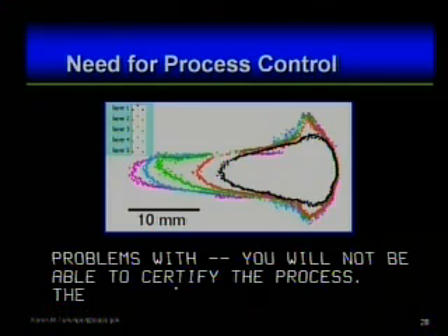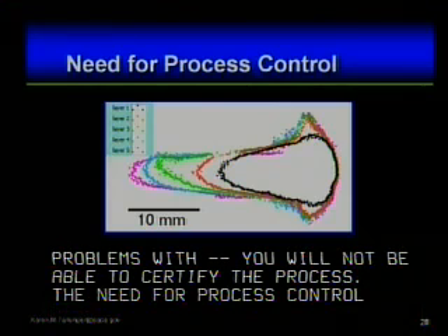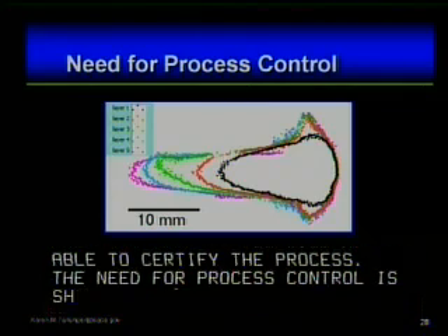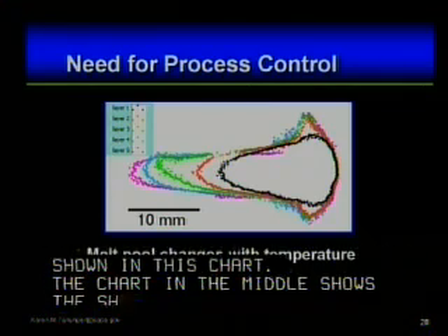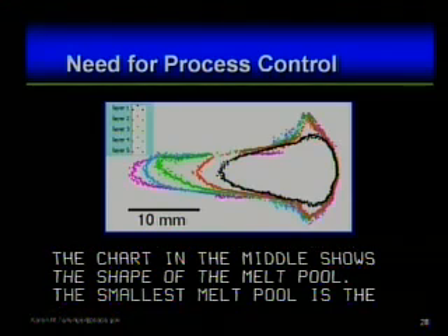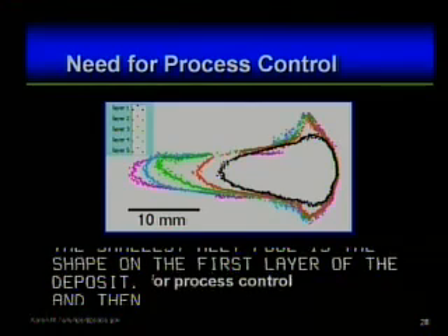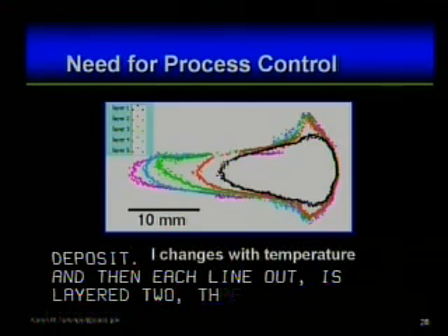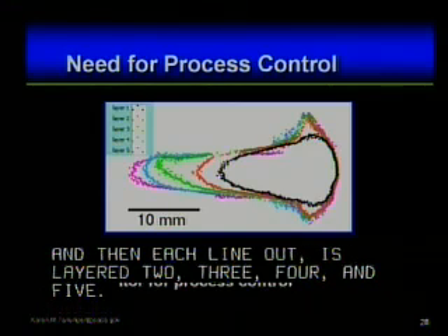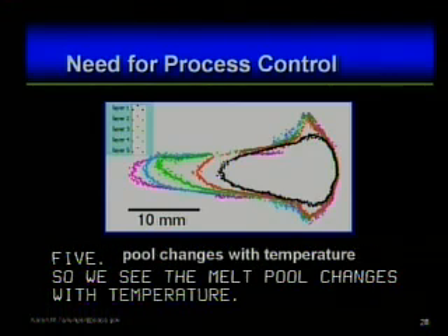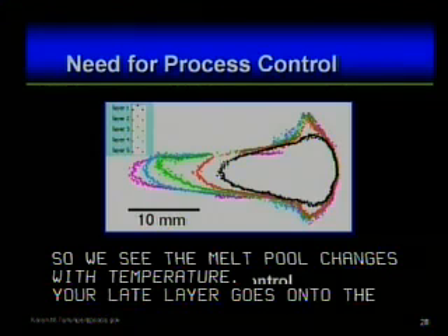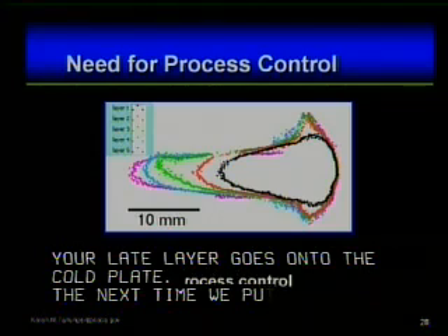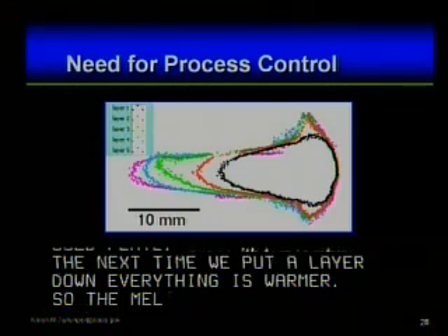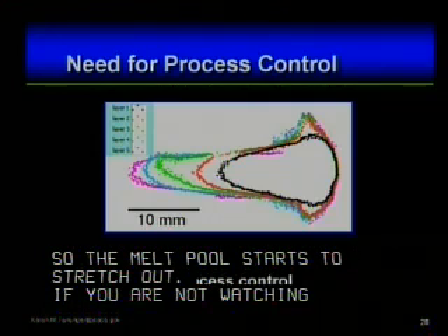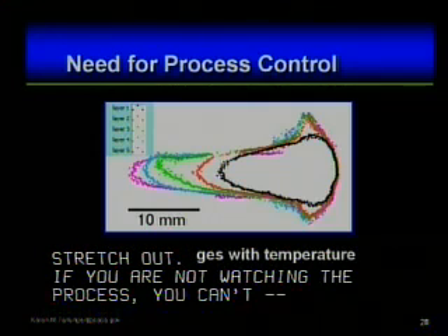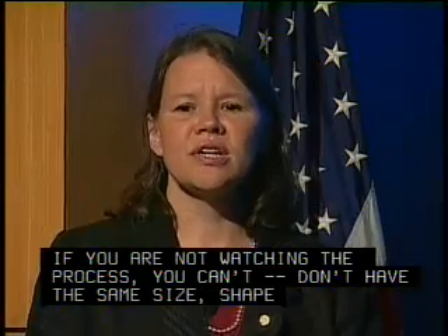The need for process control is shown in this chart. The chart in the middle shows the shape of the melt pool. The black line, the smallest melt pool, is the shape of the melt pool on the first layer of the deposit, and then each line out is layers 2, 3, 4, and 5. So what we see is the melt pool changes with temperature. Your first layer is going down onto a cold plate, and it freezes out fairly quickly. It's got a nice tight melt pool. The next time we put a layer down, everything's a little bit warmer, and so the melt pool starts to stretch out. If you don't make any changes to your process, or if you're not watching the process, you don't have the same size, shape, or temperature in the melt pool, and that's going to have ramifications for the chemistry and the distortion, residual stress, and everything else that we see.